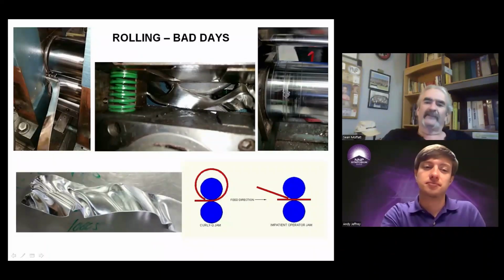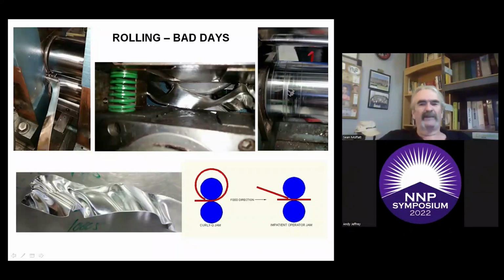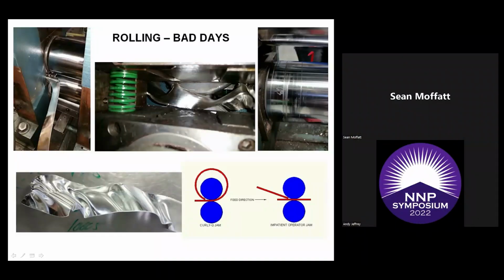And then if you have damage on your rolls, you feed something and it jams up, or there's something on your strip, like some garbage stuck in it from when you cast the strip, it can sit there and damage the roll. These two rolls have to be taken out, re-ground down to get rid of all these grooves, and repolished. If you ran strip through this with these grooves on here, that groove is going to be on your strip, and if you didn't take care of it, then it's going to end up on your finished coin.